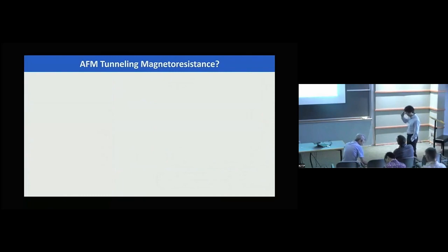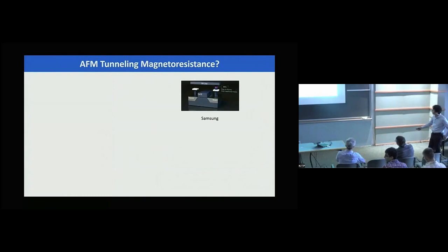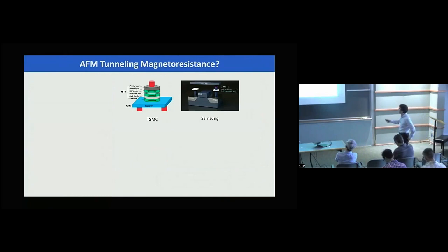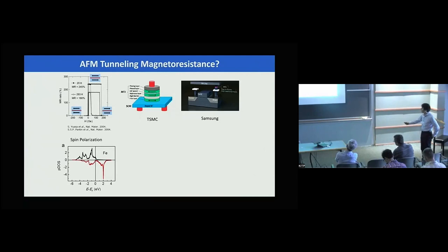So the final point I just wanted to tell you about is this quite interesting tunneling effect. Maybe just let me go through. For MRAM we know that the magnetic tunneling junction is a central part, and there are two ferromagnetic electrodes sandwiching the insulating layer, mostly MgO. They are called the free and the reference layer. And because of this spin polarization, you can see a fairly large MR. But in an antiferromagnet, obviously, there is no spin polarization. So that's the reason why no observation of this kind has been made until now.